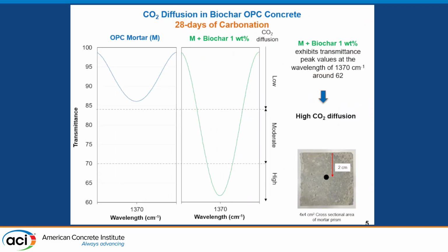So now I am comparing two samples. I am comparing a plain mortar with a mortar that was fabricated with 1% biochar. Again, that 1% was selected from our preliminary study as the best performing proportion, not in terms of CO2, but in terms of mechanical properties.